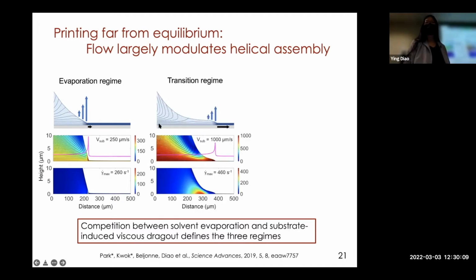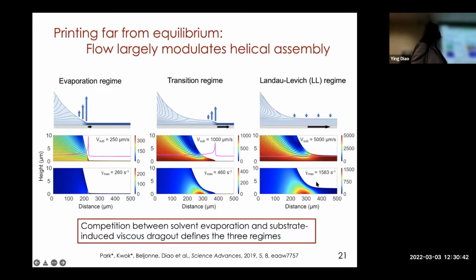If we print faster and faster, we enter a different regime where we drag out a liquid tail that cannot be fully evaporated. So the liquid will return to the bulk of the ink. And this returning flow creates a high strain rate pocket shown in this view. That's the strain rate plot, where the red color indicates high strain rate regions, whereas the blue color indicates low strain rate regions. If we print even faster, you can see that this red pocket grows bigger and bigger. As I'll show later, these red pockets have profound implications on assembly pathways.